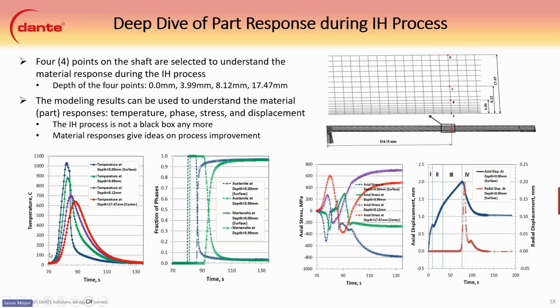Starting left to right here, we have the temperature, and so we can see that the surface reaches a little over 1,000 degrees C, and the 4 millimeter point here goes up to almost 900, and both of these transform to austenite here. These 2 points below don't transform; they only get up to about 700 degrees here. And so the depth of transformation here is really within the case. We have the fraction of phases as well, so we can see that the austenite is formed here really quickly between A and B, and then the surface transforms, and then the 4 millimeter point transforms slightly after it.